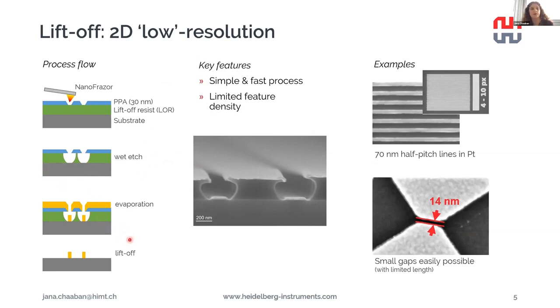And in doing so, we can deposit metals or dielectrics, any type of layers using, of course, a directional deposition method. And then by removing this liftoff resist, we get our final intended design. So this is quite a simple pattern transfer method, and it's suitable also for simple, smaller labs because it only requires wet etch chemicals in this case.